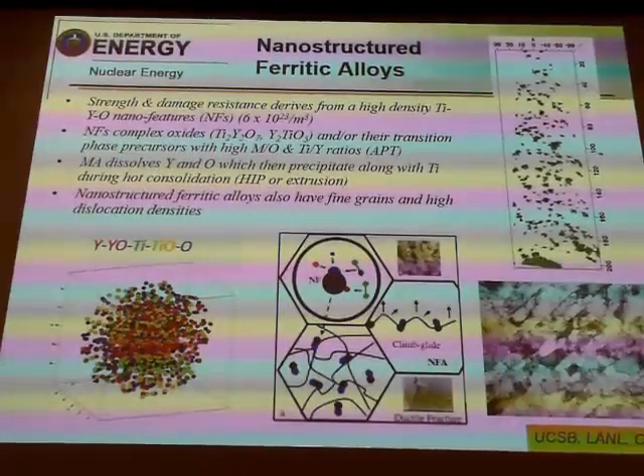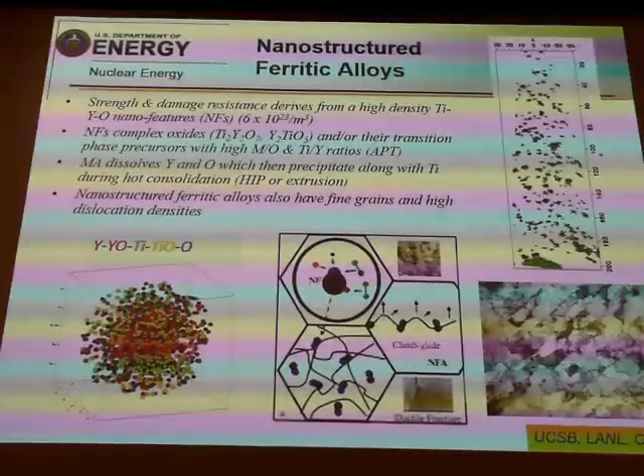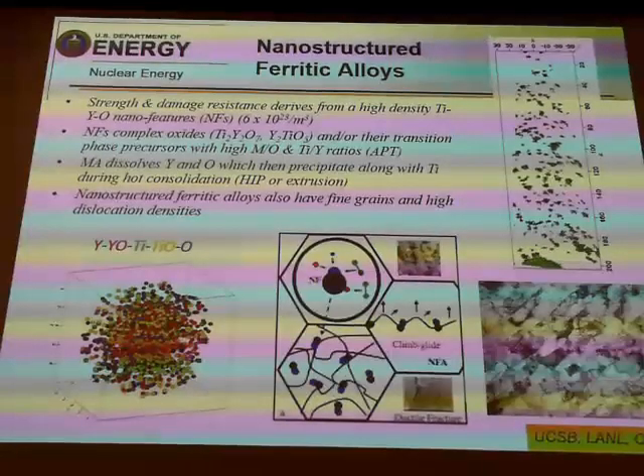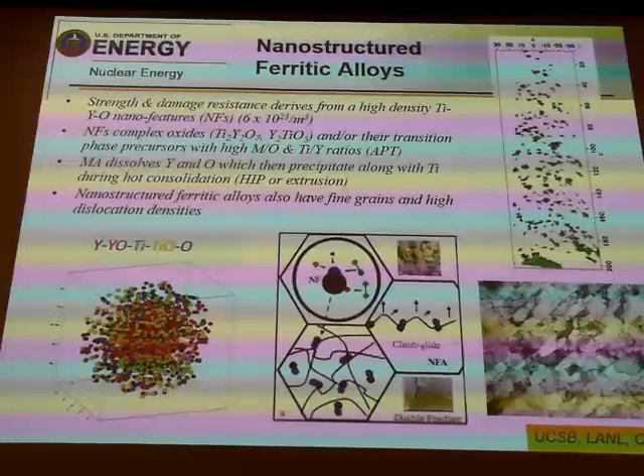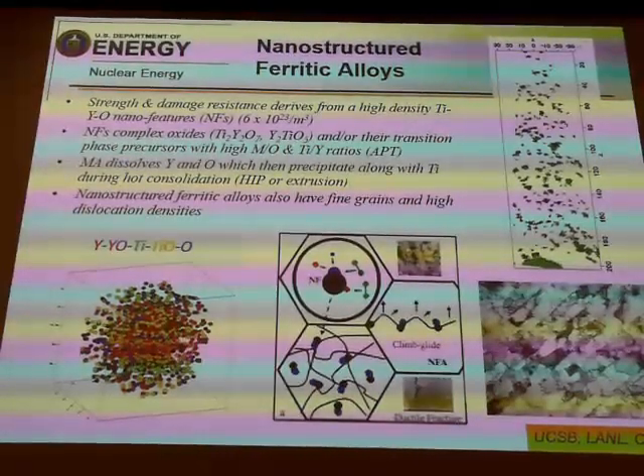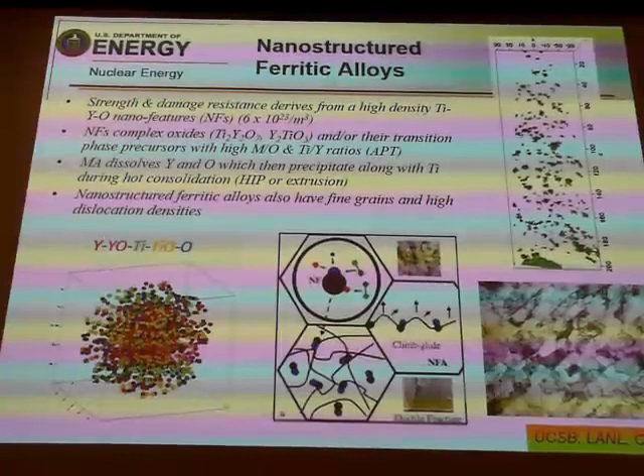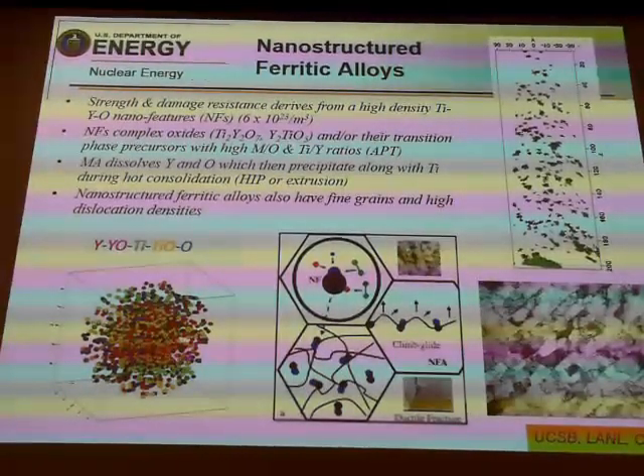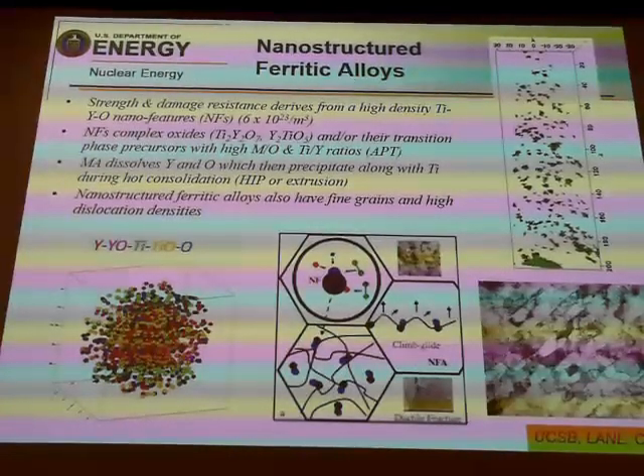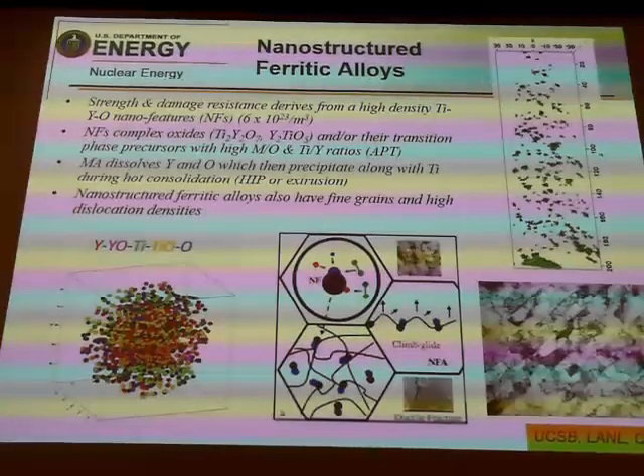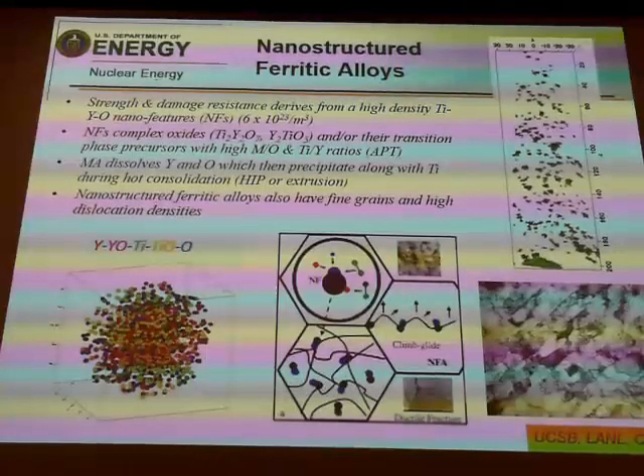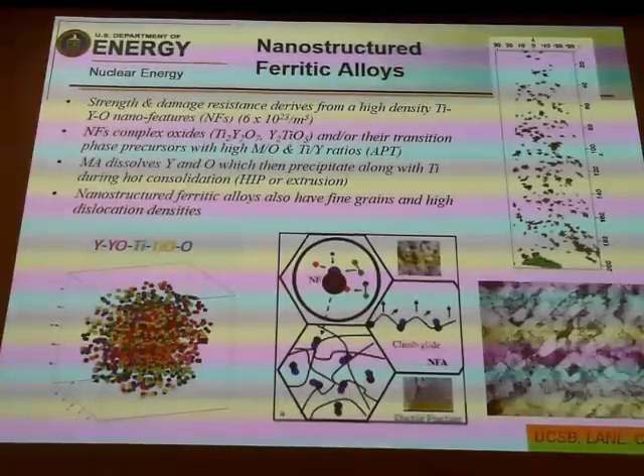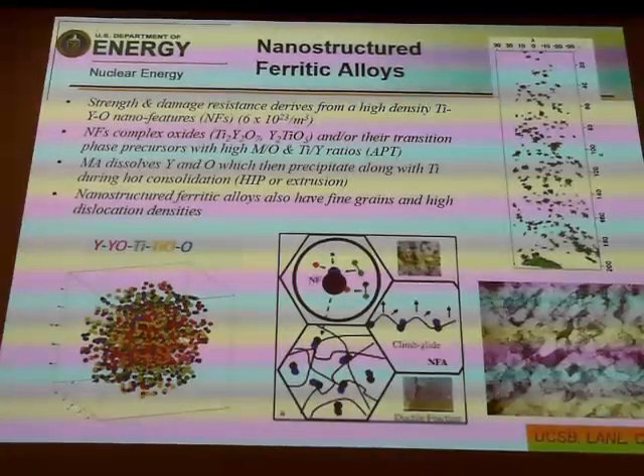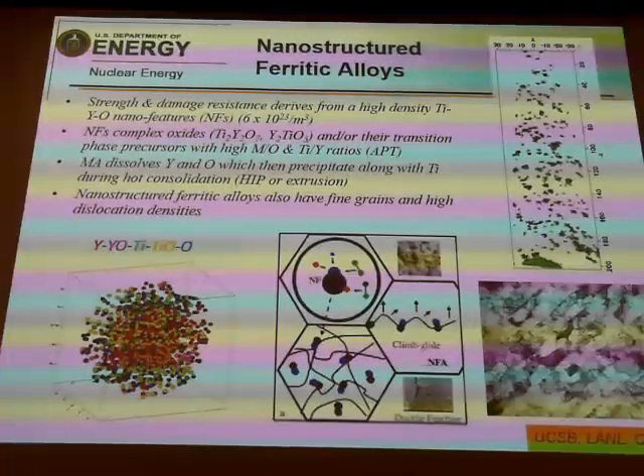There you can see all of these fine areas. On the right, those fine areas are about 2 nanometer size oxide particles that are uniformly dispersed within that tip that we did atom probe tomography on. The advantage of these nano features, typically Y2Ti2O7, is that they serve as sinks for defects, places where you recombine the interstitials and vacancies under radiation, therefore reducing the number that are within the material and reducing its amount of hardening under radiation. They also improve the creep resistance of the material as they block dislocation motion. So they make a stronger material, but also a material that's more radiation tolerant.